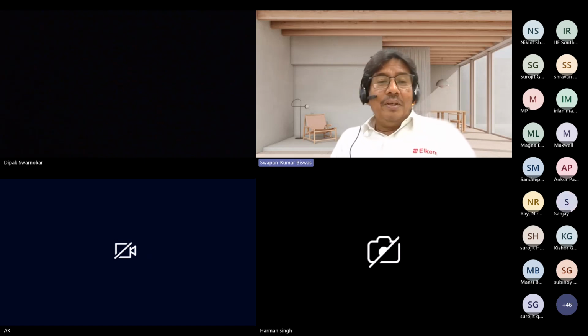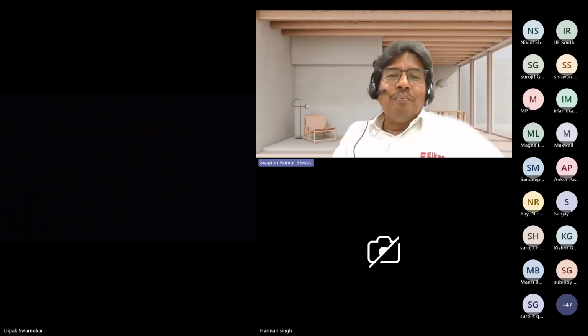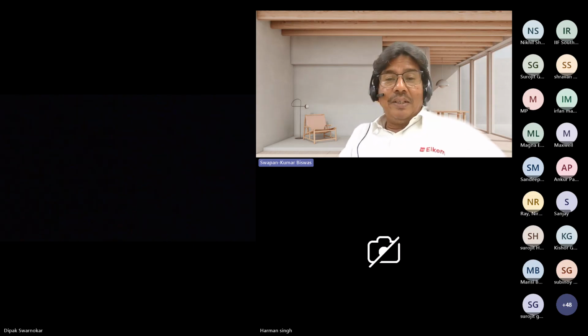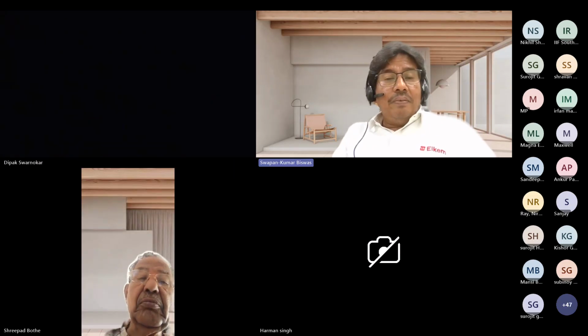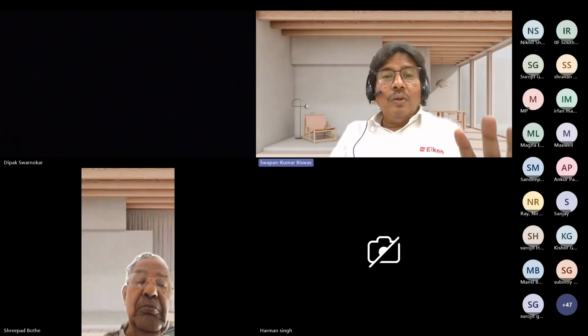Sometimes people use a little rust scrap. Maybe in pig iron also there will be some rust. This rust is iron oxide. When you add it into the melt furnace, it enhances the oxygen level inside, which also helps improve nucleation. But the addition should be limited, because it is a temporary effect, and when you add more rust scrap, it will create other problems. There is a lot of slag formation, and metal flashes may take place during addition. To avoid all this, we always suggest going with a good preconditioner that helps overcome all these challenges.